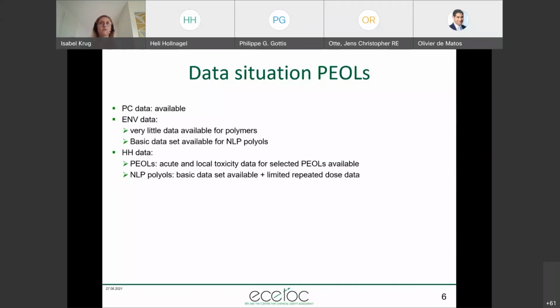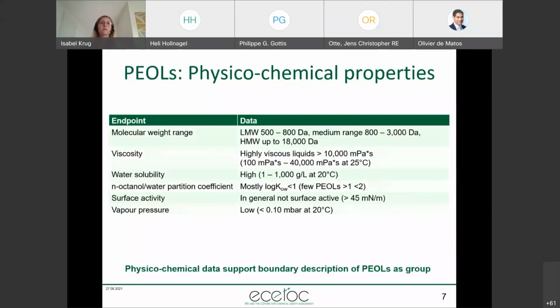So I'll jump into the data for the physicochemical properties to set the first criteria, or no, the chemical nature was the first one. The second one is the physicochemical properties. So we have a molecular weight range from higher than 500 Dalton up to the highest around 18,000 Dalton. They are highly viscous liquids with a good water solubility, and the log KOW is below 1. Only for a few polyols it is ranging between 1 and 2, and in general they are not surface active, and they also show a low vapor pressure.